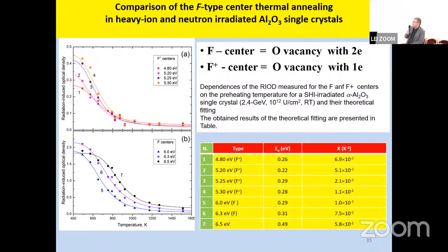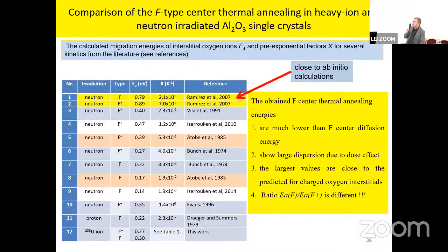This is just the behavior of the optical density as a function of the temperature. Then we analyzed all this data using our model. So we obtained quite low activation energy for defect annealing. But what to do? This is a table showing you similar annealing data from all available papers. What we can see from here is that there is a huge difference between different experiments. But what is important, only in one paper is this data quite close to the ab initio calculation.